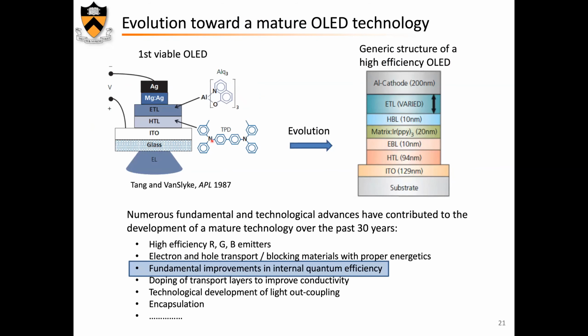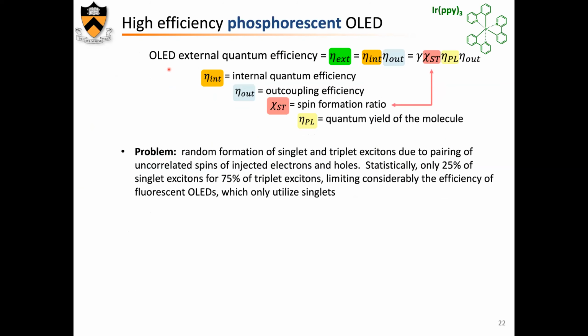When you look at the efficiency of the device, this external quantum efficiency is the product of internal quantum efficiency times the outcoupling efficiency. Outcoupling is a real difficult problem. You produce a lot of light in the device, but you really have to get it out, otherwise it's of no use. But looking back at this part here, the internal quantum efficiency has a spin formation ratio and of course the quantum yield of the molecule.